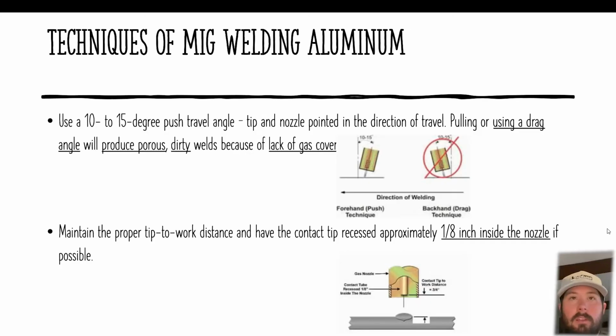So a few techniques for welding on aluminum with MIG. You want to use a 10 to 15 degree push angle, push, not drag, with the tip and nozzle pointed in the direction of travel. Using a drag will result in dirty and porous welds because of lack of gas coverage. So maintain the proper tip to work distance, and you want to have the contact tip approximately 1/8 inch inside of the nozzle if possible.